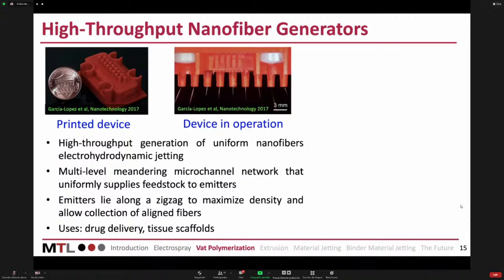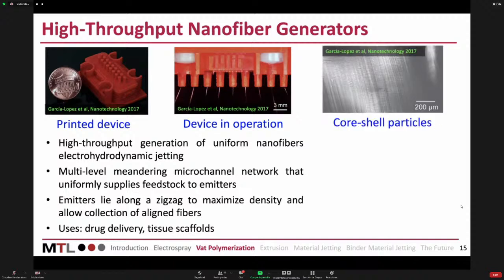So what you see is each of the emitters is producing a jet, and those jets are going to get whipped and stretched because of these electrohydrodynamic effects. And if you have a rotating drum, then you can collect them aligned. So you can get these striations in the film. And this is something that you can use, for example, for tissue scaffolding. That pre-ordered structure is actually very good for that.